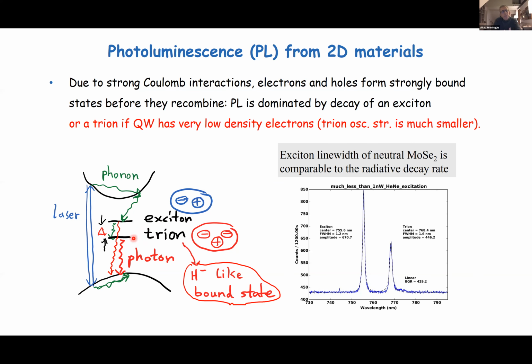Now, what is also possible, if we have electrons in the system, is that the exciton can bind to one of these electrons and form a bound state, which is the counterpart of the H- ion. If you have seen this in atomic physics, this is a rather peculiar ion where the hydrogen atom has a single bound state for capturing an electron, provided the electrons form a singlet. In photoluminescence, this binding energy is about 25 milli-electron volts. Even though the trion has very weak oscillator strength, and I'll tell you why, it can appear prominently because it has lower energy than the exciton.